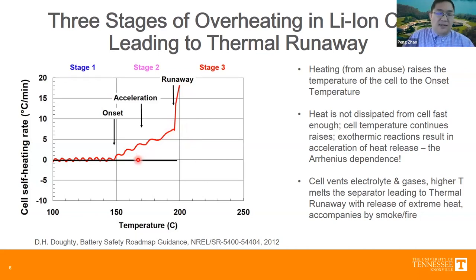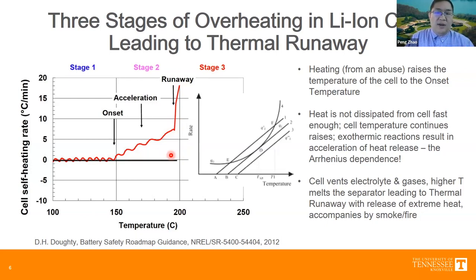Eventually, I think this basically shows that thermal runaway has a very similar nature to the ignition problem. This phenomenon can be explained using the widely known Semenov criterion. Basically, if you consider that the chemical heat release has Arrhenius temperature dependence, and any cooling process gives you a near linear temperature dependence, the threshold condition is given by the tangential point of these two curves. And starting from there, you can see that any disturbance will give you a much faster increase of the chemical heat release compared with heat loss.